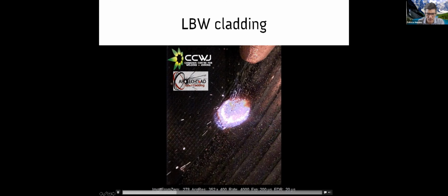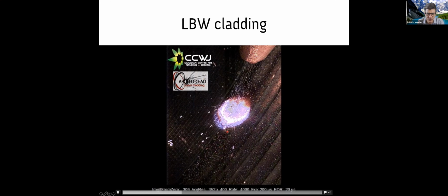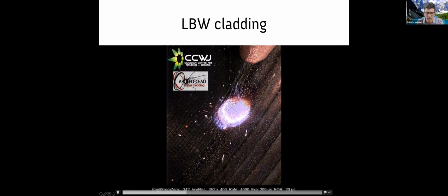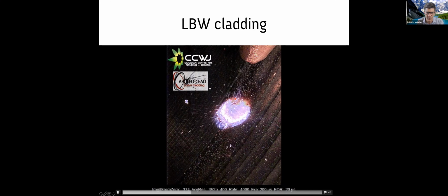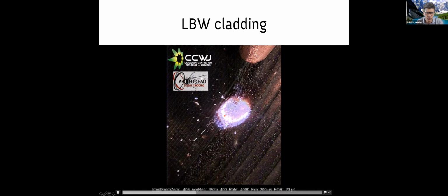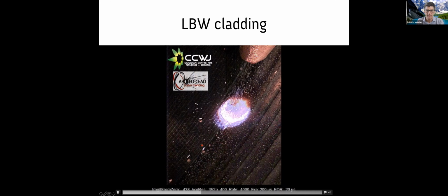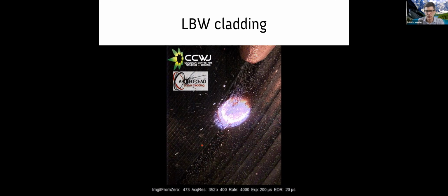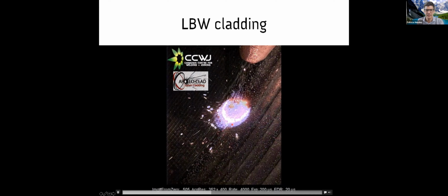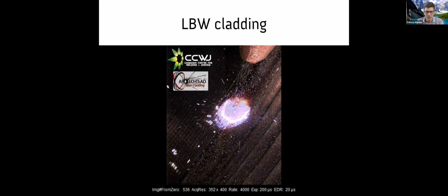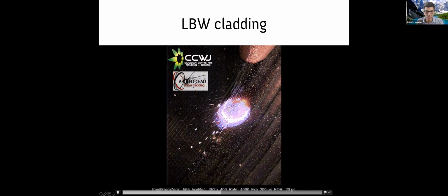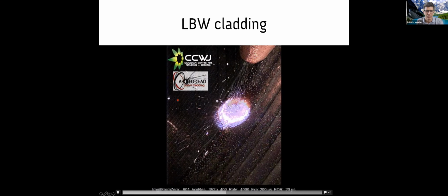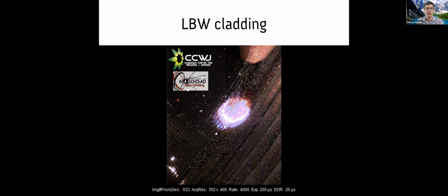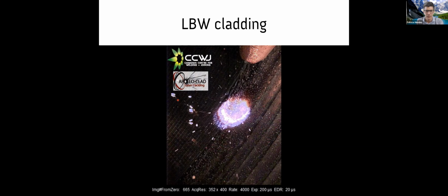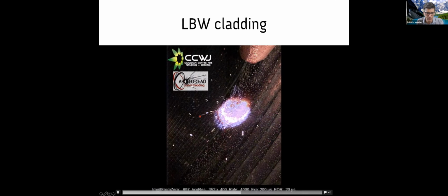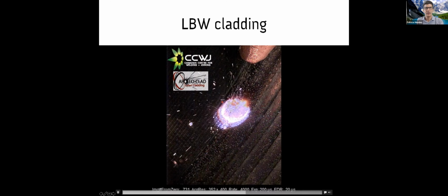What you get to see here are the clad beads. Here is the base metal. Here is the weld pool, and the progression is moving from top right to bottom left. This cladding is nickel tungsten carbide. So the powders you see coming are a mixture of nickel powders and tungsten carbide powders. And you see kind of two types of spatter. The globulars like this, we believe those are molten nickel droplets coming out. And the other ones that you see that are much smaller, moving fast, those are tungsten carbide particles.